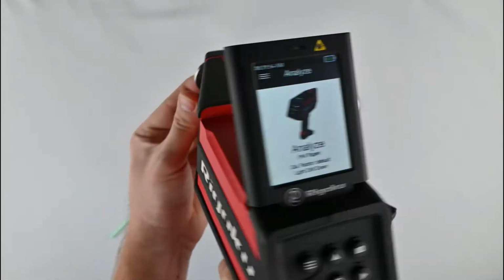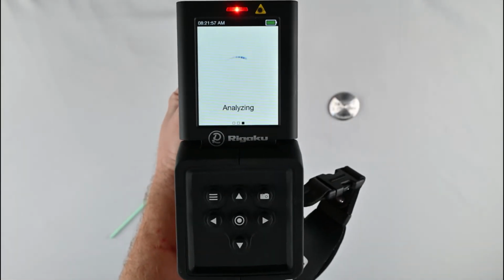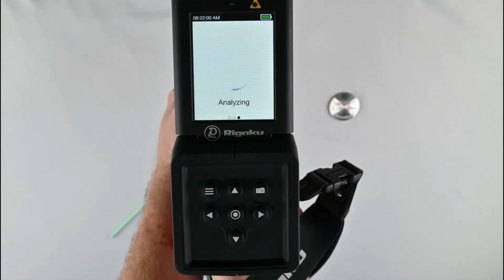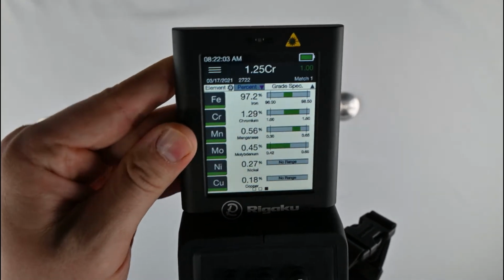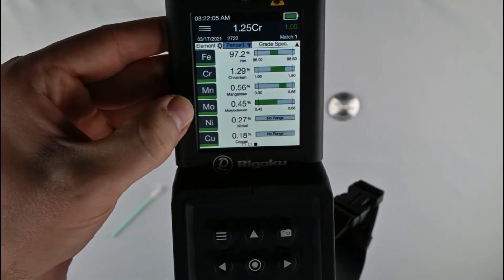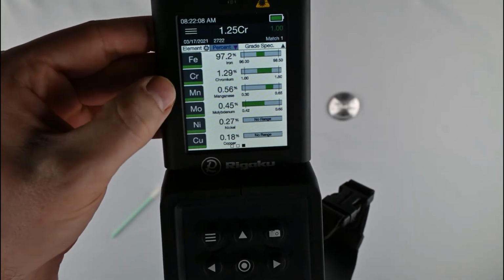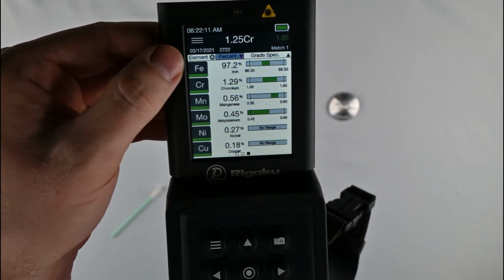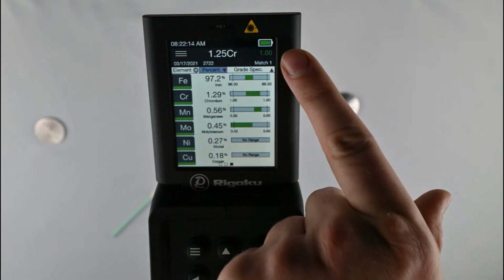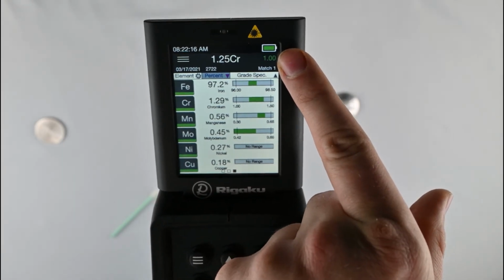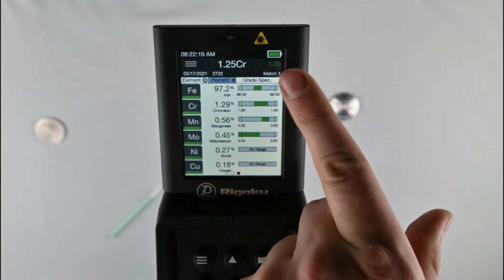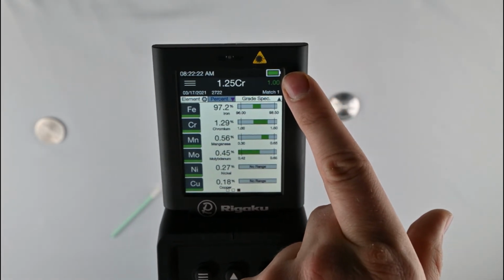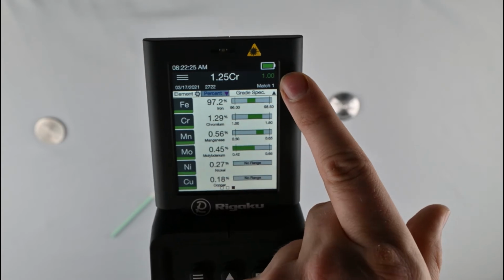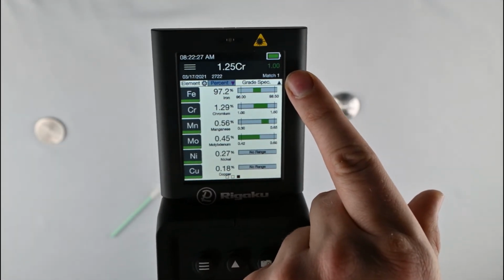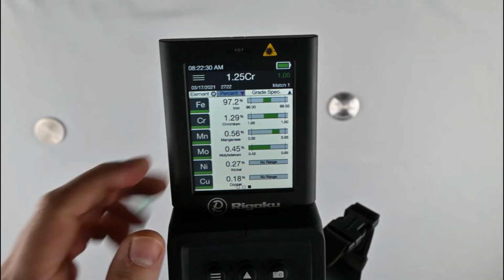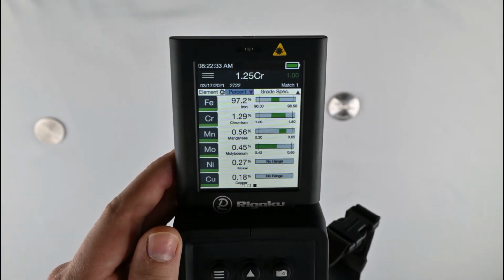We're going to approach that with the analyzer, and we'll do a test here. Okay, so now as you can see here, that name 1 1/4 chrome and half moly, we're right at about those levels. There's a little bit extra manganese in here, but it's mostly iron. And it's a pretty plain alloy. You can see up here in the upper right hand corner, first of all, we call this 1 1/4 chrome at Rigaku, and then we have this 100% match. So you can see it's easily sortable with handheld LIBS, and we use this 1 1/4 chrome name because we can see both the forged grades and the cast specs in the field.